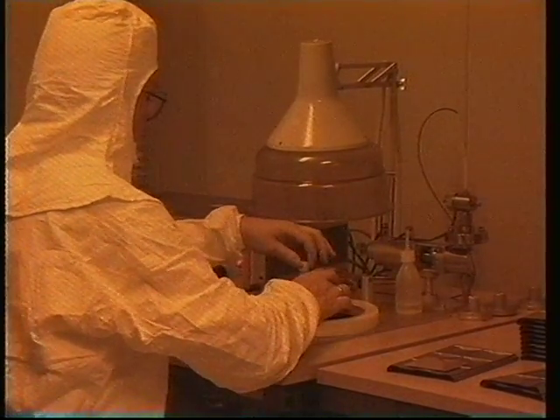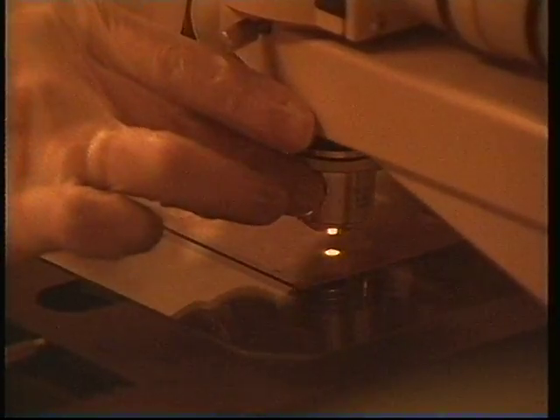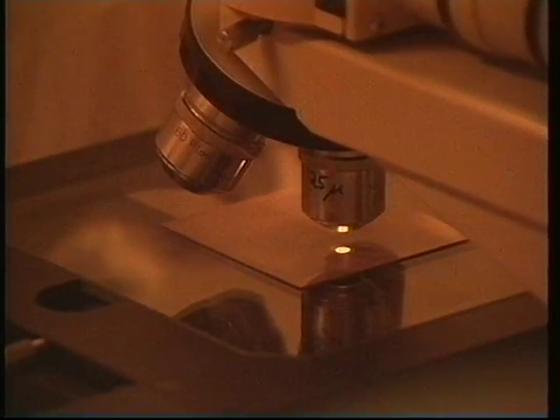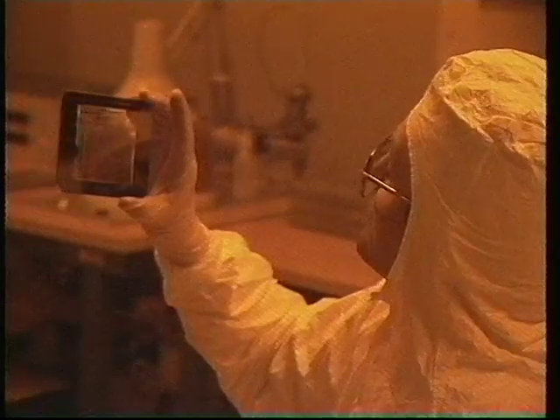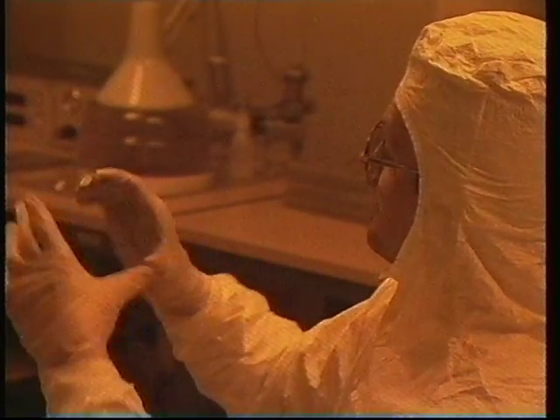In the photoresist spinner, a few drops of photosensitive liquid, called photoresist, are deposited in the center of the substrate. Then the substrate is rotated at high speed, and the resist spreads out to a thin, uniform layer covering the whole substrate. The yellow light in this room does not affect the photoresist, and the operator wears special clothing to prevent dust particles from contaminating the surface.